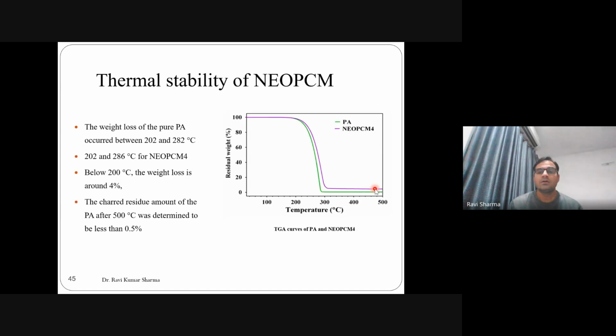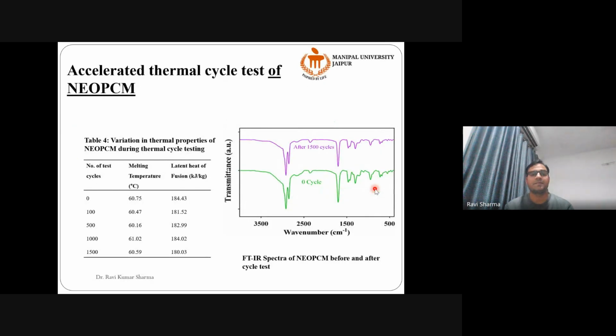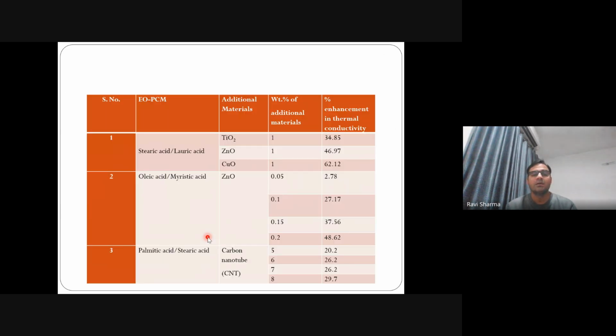This is the thermal stability of nano-enhanced PCM. When we add nanoparticle into the PCM, the thermal stability increases. A thermal cycling test was also done for this material for 1500 cycles, and the material was pretty stable. Even after 1500 cycles, only 2% of the latent heat was decreased.